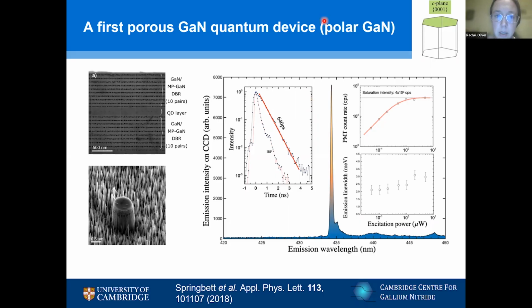I've got one in the Q&A, which says, what paths forward do you see for integrating these quantum dots in photonic circuits? There are lots of different approaches you could take. I think the A-plane quantum dots are perhaps more difficult to think about how we might do the integration. For the C-plane quantum dots, we can grow them on sapphire, as most of the devices I've shown here, but we can also grow them on silicon. We do quite a lot of work in the LED space on separating the gallium nitride membrane from the substrate, and then using transfer printing techniques, you can pick up a disk, which might be a cavity, and put it adjacent to a waveguide and start to build a photonic circuit.